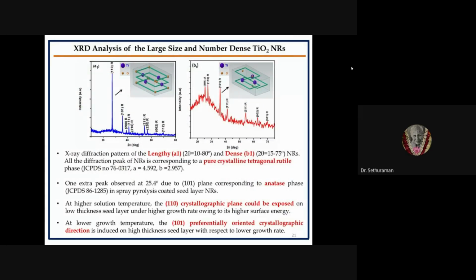We have taken the XRD pattern for the seed layer as well as the nanorods, and from the XRD pattern we confirmed the rutile phase of TiO2. In the case of the TiO2 seed layer XRD, we confirmed the anatase phase also, but in the nanorods completely rutile phase of TiO2 is obtained. The nanorod corresponds to the crystalline tetragonal rutile phase. The one extra peak I told you was observed in the seed layer XRD belongs to the anatase phase.